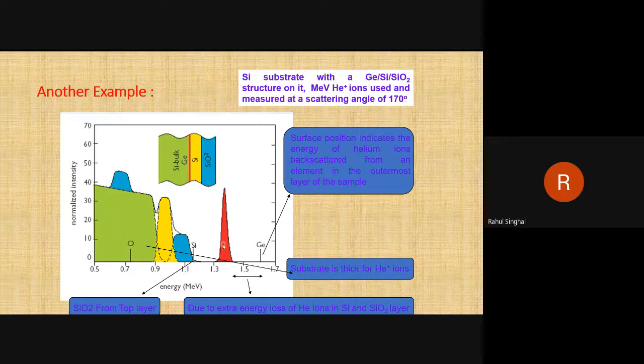Because we have germanium only at one layer, we are getting a very good Gaussian peak of germanium. After that we have the silicon peak, because the mass of silicon is lesser than germanium, but in principle it should come at further lower energy, like here. But SiO2 silicon is from three different places: one from the surface, one from the inner layer, and one from the substrate. So correspondingly, we are getting different peaks. The silicon which is present on the surface, we are getting this peak here.